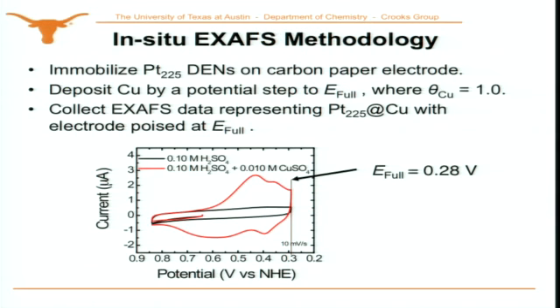Okay, so here's the approach we use for doing the XAFS experiments. As I said, the DENs are immobilized on a carbon paper electrode. Copper is deposited underpotentially by stepping to this potential we call E full. E full is the potential at which we have a full copper UPD monolayer. If we went any further out here, we'd start depositing bulk copper. So we step from this potential to this potential, wait for the current to die away, and now we're ready to collect XAFS data. It takes about 2 hours to collect enough data.